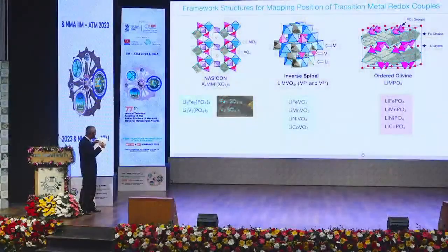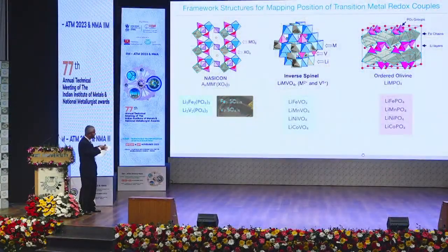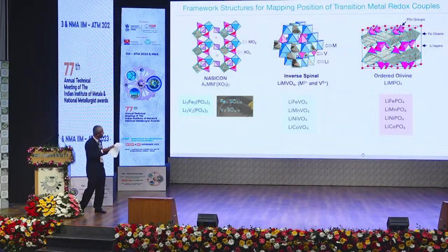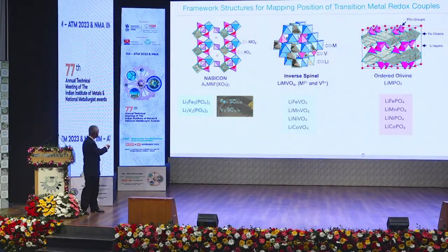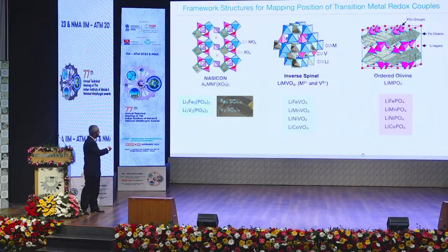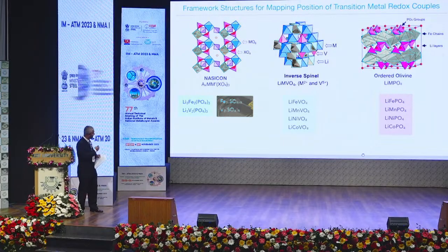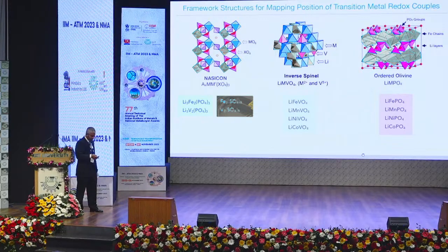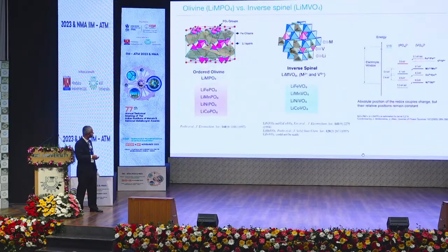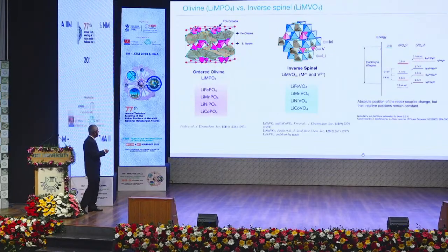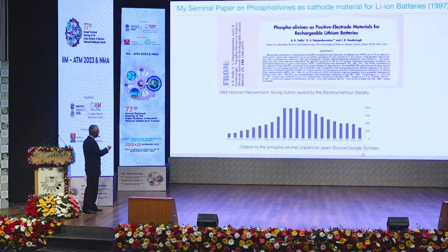We found, so my topic for the PhD was basically mapping all these redox potentials of various transition metal elements in different structures, and to understand how these different polyanions like phosphates and sulfates and the structures are affecting this voltage. We can see that we can make several materials in the same structure, and I can find out where the manganese, iron, nickel, cobalt, all these redox potentials are in different structures.